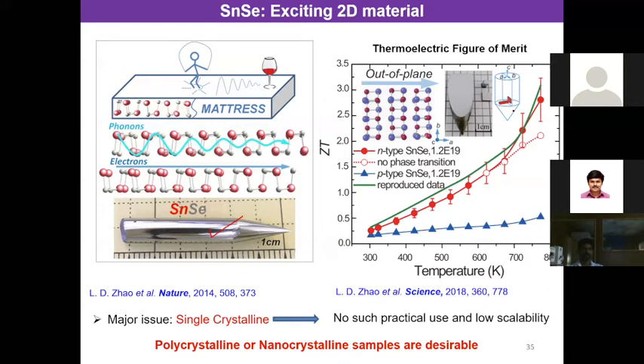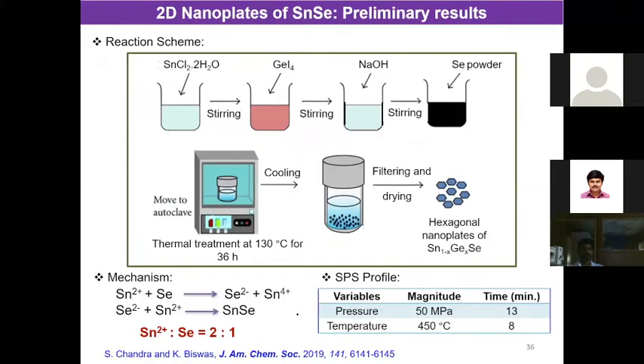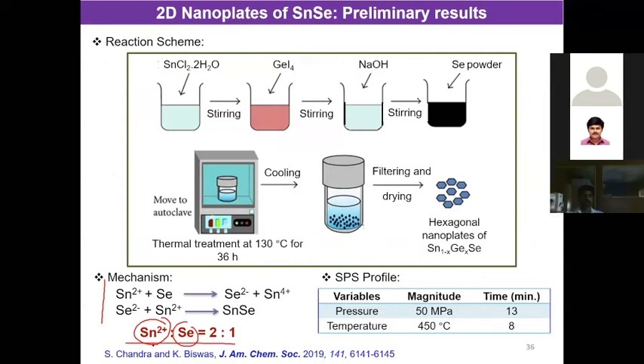Okay, so that we know, but for real purpose, this single crystal cannot be used. We have to have polycrystal or nanocrystal. So in our lab, first time we have synthesized germanium doped tin selenide nanoplates by a simple autoclave reaction. But the trick is that you have to have a 2:1 tin versus selenium ratio, so that some simple chemistry can happen. That means it can act as a reactant as well as a reducing agent. If you want the details about the synthesis, please read the paper.